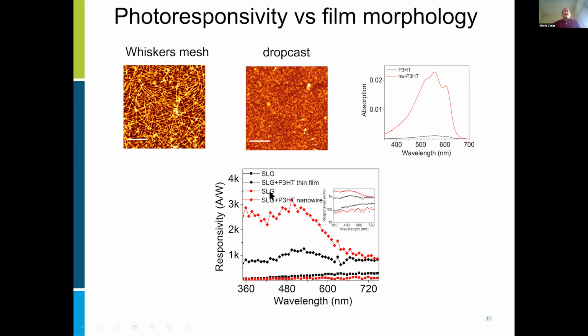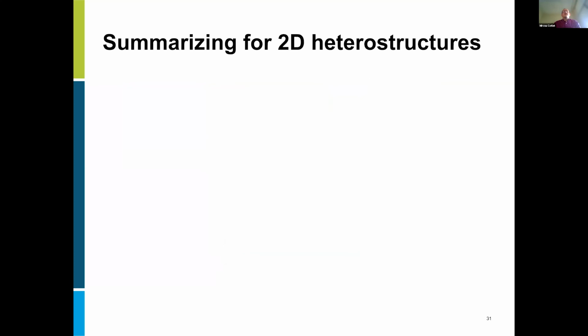hybrids, we see that the nanowire, here in red, has the highest responsivity versus the thin film polymer and versus the pristine devices that are based on single layer graphene. So a straightforward method to move from a thin polymer film into a nanowire mesh, where controlling these voids can produce substantial improvement in these properties. And this brings me basically to pretty much the end of my talk today.